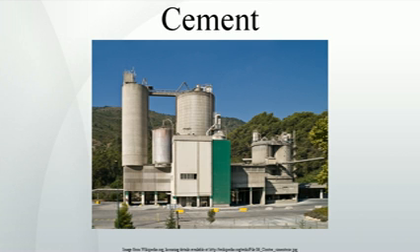Heavy metals present in the clinker. The presence of heavy metals in the clinker arises both from the natural raw materials and from the use of recycled byproducts or alternative fuels. The high pH prevailing in the cement porewater, 12.5 < pH < 13.5, limits the mobility of many heavy metals by decreasing their solubility and increasing their sorption onto the cement mineral phases. Nickel, zinc and lead are commonly found in cement in non-negligible concentrations.